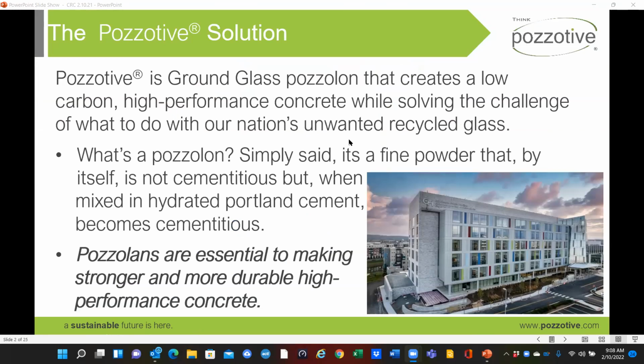So just broadly, to explain what we're doing with glass in concrete, I think there's a misperception out there that concrete's a place just to bury glass. If you don't have a better use for it, put it in asphalt, put it in concrete or whatever. But it's different. It's not just an inert aggregate. There's a chemical reaction that occurs here, making ground glass so small that it becomes a pozzolan. And a pozzolan, simply said, is a fine powder that by itself doesn't do anything. It's not cementitious, but when you mix it with water and cement, it becomes cementitious. In effect, a chemical reaction occurs that creates more cement. That's why it's different than just using it as a filler, a sand, or an aggregate. At this size, a chemical reaction occurs, and that's why it's exciting for its ability to replace the actual cement component in concrete.